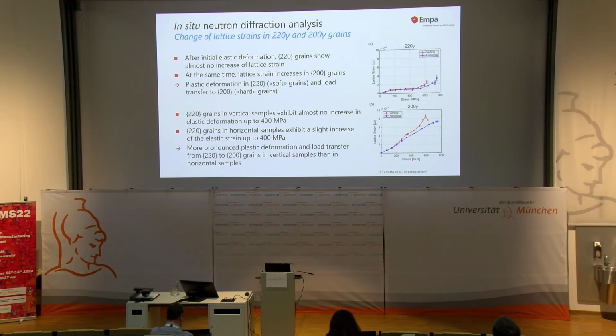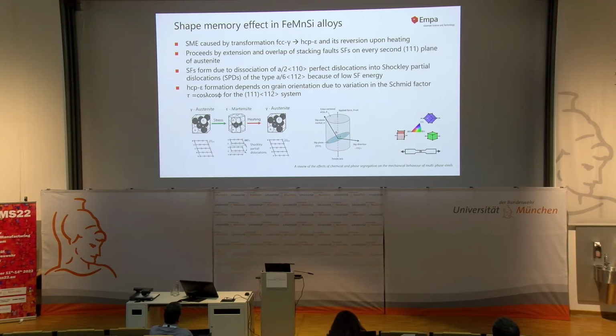transfer. At a certain stress, the 200 can no longer withstand that. They also start to transform, and that's induced here. So going back to the shape memory effect I mentioned, we have this phase transformation. This is actually the result of the extension and overlap of stacking faults on every second 1-1-1 plane. And these stacking faults form due to the dissociation of perfect dislocations into partial dislocations.